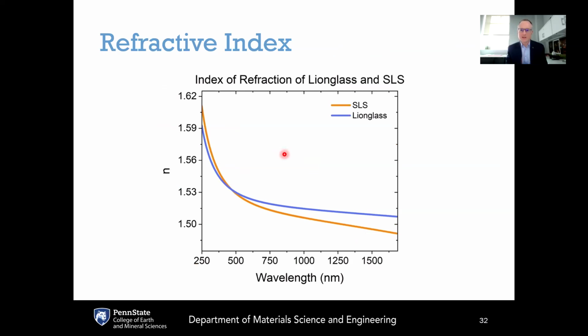If you just look at LionGlass, it looks very similar to soda lime silicate because the index of refraction is actually quite similar. The dispersion is actually slightly less for LionGlass. You can see that the refractive index is more consistent across the range of wavelengths compared to soda lime. The one thing that you'll note that's different with LionGlass is that it's actually clearer. And that's because there is less iron contamination in the batch materials, but also LionGlass colors less for an equivalent amount of iron. So whereas you may get a greenish tint with soda lime and basically have to pay extra to get the low iron version of soda lime, with LionGlass you get that automatically because it suppresses